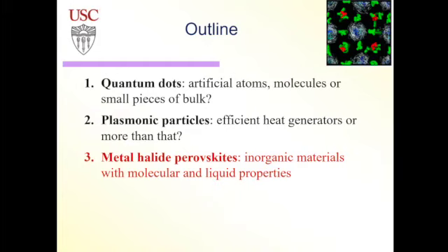But the opposite process is not very efficient because Coulomb attractions are strong, the dielectric constant is weak. So when you photoexcite organic matter, it's hard to separate charges. You lose a lot of extra energy. You need extra energy to separate charges. So if you have inorganic lattice, just like silicon or cadmium selenide, it creates good conditions for charge separation and also charge transfer. But it has this molecule in the middle that rotates, has dipole moment. So it's almost like a liquid, right?